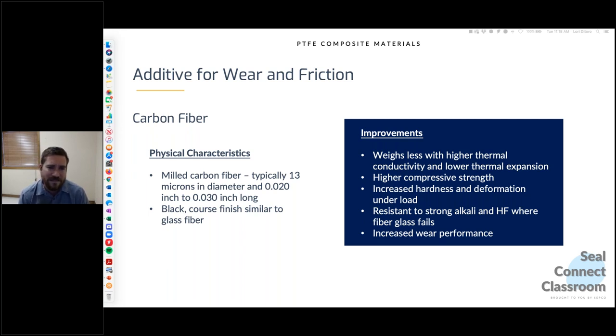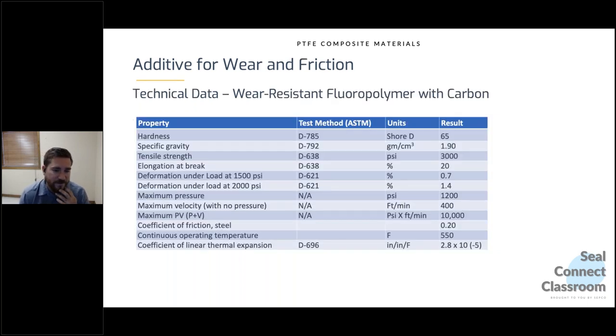Improvements: it weighs less with higher thermal conductivity and lower thermal expansion. So we're going to get some better thermal properties, some lower thermal expansion, meaning it's not going to move quite as much as the temperature increases. Of course, higher compressive strength, increased hardness, increased deformation under load. And when you add carbon fiber to PTFE, it maintains its strong alkali and hydrofluoric acid resistance, whereas glass fiber will not do that. So that's the advantage of carbon fiber over, say, a fiberglass, and we'll talk a little bit about that in a little bit.